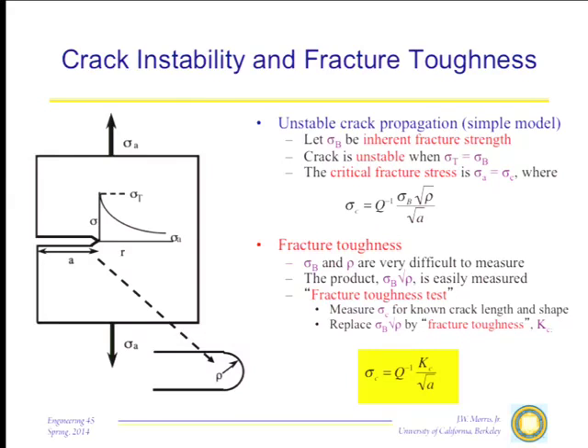And if the crack ever becomes unstable because of the load you've got on it, it's going to really be unstable. If I start to grow this crack, the crack gets longer. As the crack gets longer, the crack tip stress goes up. So if I ever get the crack tip stress on here that's big enough to propagate the crack, unless something else intervenes, that crack is gone. This sample is broken. So this sample is going to break by crack instability when the crack tip stress is equal to the breaking stress sigma b.